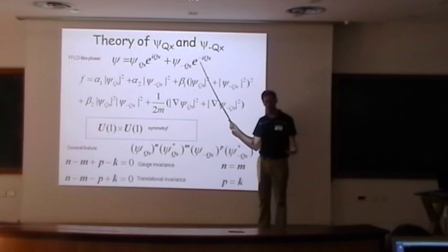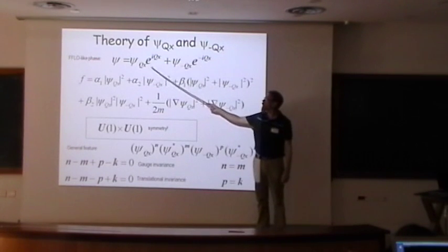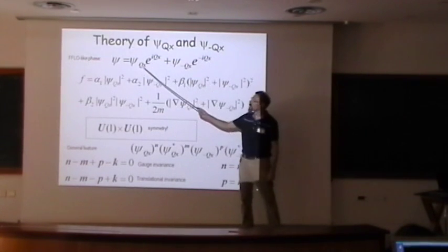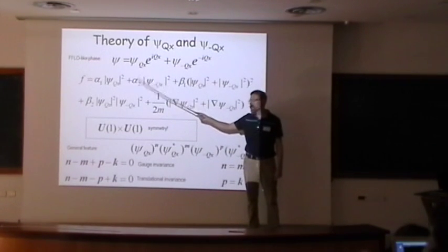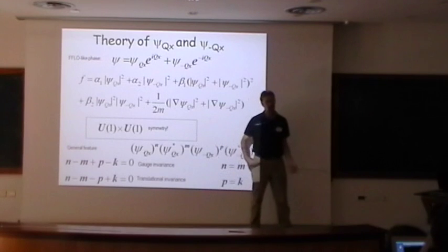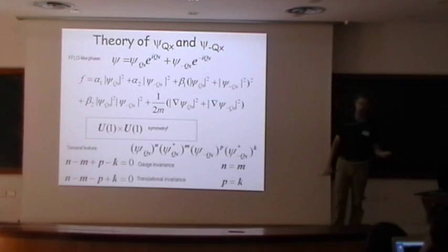And so in the actual FFLO superconductor, not even in these other FFLO cases, you do have exactly that. You have e to the iqx plus e to the minus iqx. But in principle, you should treat each component as a separate degree of freedom, and then you get this two-component theory. So even in an FFLO superconductor, you get exactly half quantum vortices. But in these non-centrosymmetric cases, they can differ from one half. You can get two different types of fractional vortices whose sum is one usual flux quantum.